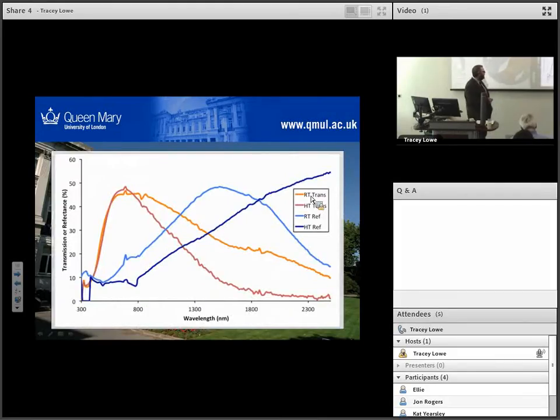Looking at the thermochromic properties - these are a little bit of a mess. We can see we've got some change in transmission and some corresponding change. Actually the reflectance data isn't particularly useful because we're depositing onto fluorine doped tin oxide, which starts to have some reflective behaviour in the infrared. So I'd take the reflectance data with a pinch of salt, but there's definitely a change in the transmission.